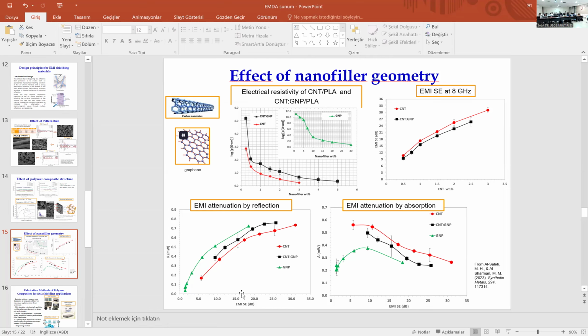Carbon nanotube-based composites show superior electrical properties compared to graphene-based composites due to the rod-like geometry of the carbon nanotubes. This facilitates the dispersion of the carbon nanotube particles and the formation of the carbon nanotube conductive network within the polymer matrix. The rod-like geometry and the smaller surface area of carbon nanotubes compared to graphene decrease the reflection of the radiation at the composite external surfaces. In addition, the conductive carbon nanotube network within the polymer matrix has facilitated the absorption of the EMI radiation.